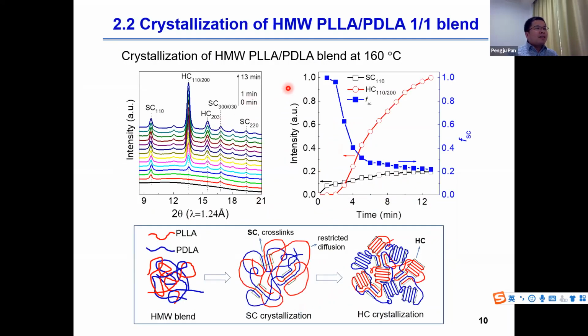Because both the stereocomplex and the homocrystal can be crystallized in the temperature range from 80 to 160 degrees C, we are curious about the competition between these two crystallization processes. We studied the crystallization process of the blend at 160 degrees C by the WAXD. In the crystallization process, we first observe the diffraction peak of stereocomplex and then observe the diffraction peak of homocrystal. The intensity of homocrystal increased more significantly than stereocomplex in the later stage of crystallization.